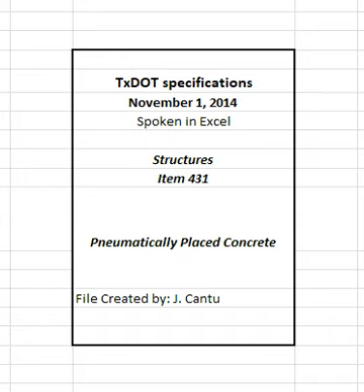Hold the nozzle approximately 2 to 4 feet from the surface and position it so the concrete impinges nearly at right angles to the surface being covered. Use shooting strips to ensure straight lines, square corners, and a plain surface of concrete. Place to keep the trapping of rebound to a minimum.